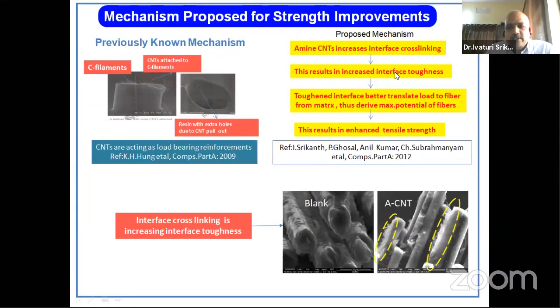But our study shows that even with very good dispersion, at 0.5% the mechanical properties increase only 5 to 10%. Beyond that, even if there is good dispersion, the mechanical properties will come down. So we have questioned the mechanism. We proposed that improvements are mainly due to the interface toughness. The nanotubes improve the interface toughness because of improved cross-linking at the interface, and because of improved cross-linking, the weak interface becomes strong. Even if the nanotubes get well dispersed, you cannot improve the mechanics further. The nanotubes are not acting as load-bearing members.